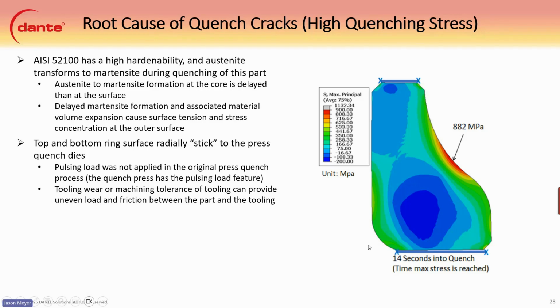They kind of stick to the press-quench dies. And we found that the pulsing load is not applied during the press-quench, even though it does have the pulsing feature. A lot of things can cause it to stick here. Some of them are the tooling wear of the actual press from continual use. It could cause uneven load or friction on the part while it's being processed. They could also have machining tolerance for the ring itself. It could be a little off, and then they would have higher and lower load regions, causing more friction in the tooling as well.